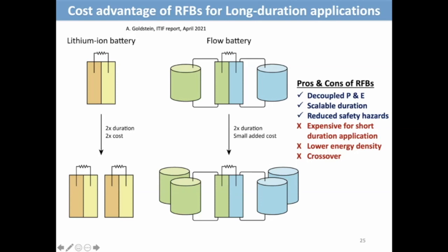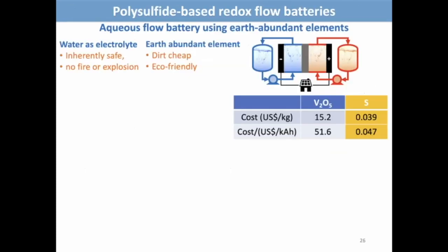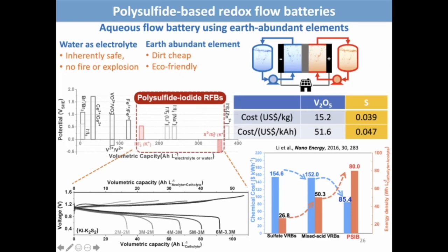However, flow batteries currently are still struggling with a lot of challenges, including being expensive for short duration applications. They have lower energy density and suffer from crossover, which becomes a problem for the cycle life of the redox flow battery. So in our group, to address this issue, we're looking at a very low cost, earth abundant element, sulfur. A polysulfide-based redox flow battery is very safe and cheap thanks to sulfur, which is extremely low cost and has high capacity. You can see the cost per charge is significantly lower than that of vanadium used in a vanadium redox flow battery. So using polysulfide is in fact a great option.